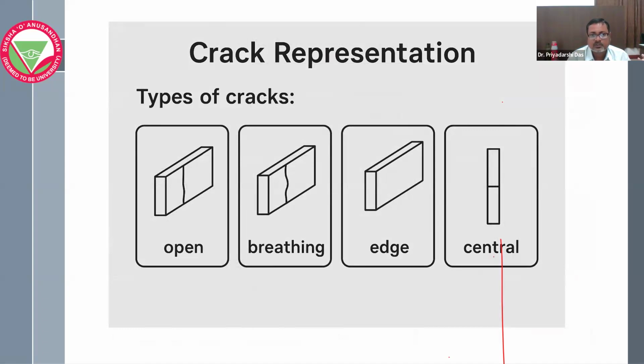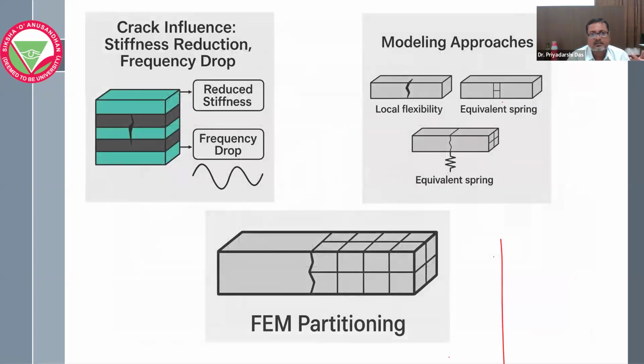The different types of cracks are the open crack, breathing crack, edge crack, and central crack. The crack influence here is the crack that is formed inside the structure, that is an intra-ply failure. And due to that intra-ply failure, the stiffness will be reduced, and since the stiffness is reduced, the frequency will drop. That means frequency analysis is a non-destructive tool. If the structure is intact, it will hold its frequency. If the structure is disintegrated, its frequency will drop. From that frequency drop, you can easily analyze that something went wrong with the structure, and somewhere the structure has been disintegrated, and we need to find out. So the frequency is passed through the structure. Where the frequency is obstructed, at that point you can look at the disintegration or that crack.